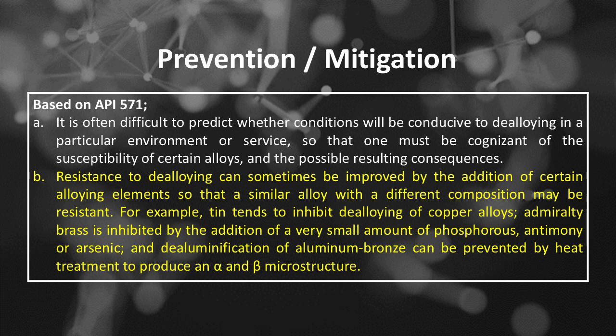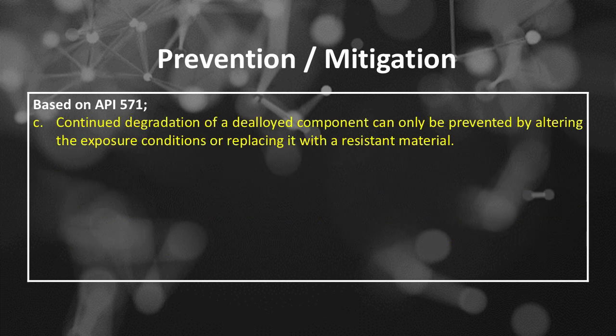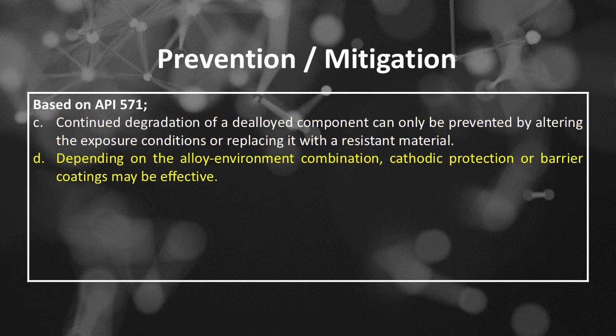For example, tin tends to inhibit dealloying of copper alloys. Admiralty brass is inhibited by the addition of a very small amount of phosphorus, antimony or arsenic, and dealuminification of aluminum bronze can be prevented by heat treatment to produce an alpha and beta microstructure. Number C. Continued degradation of a dealloyed component can only be prevented by altering the exposure conditions or replacing it with a resistant material. Number D. Depending on the alloy-environment combination, cathodic protection or barrier coatings may be effective.